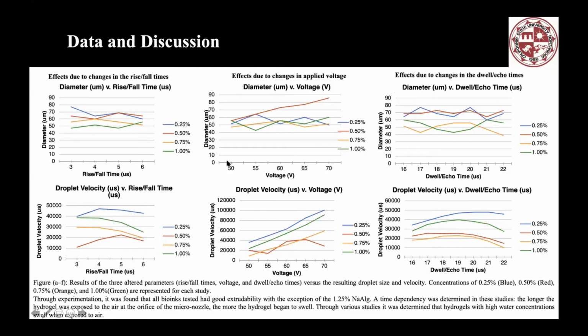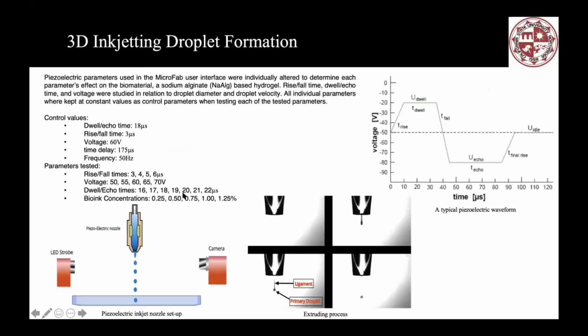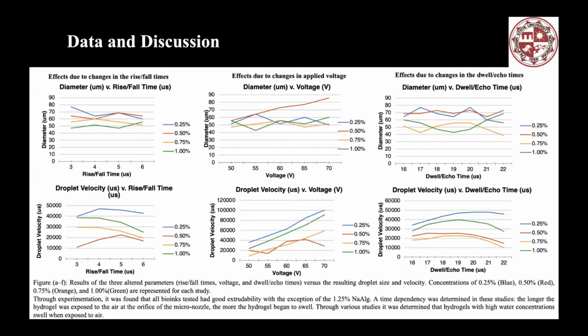So we use these samples, with different concentrations, like these 5 different concentrations, and these 7 different times. For voltage, we pick these 5 different voltages, and then these are 4 different rise and fall times. Here we're trying to see the effects: here is due to the change in the rise and fall times, here is due to the change in the applied voltage, and here is due to the change in the echo time, the dwell time.